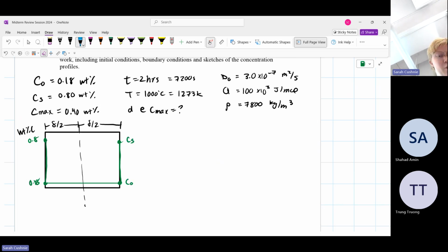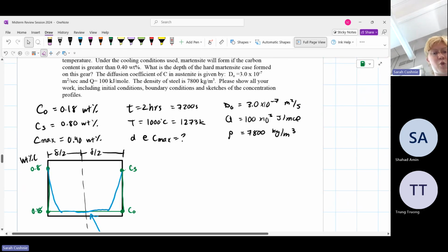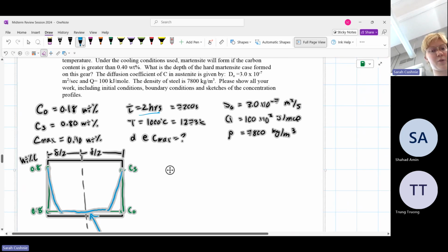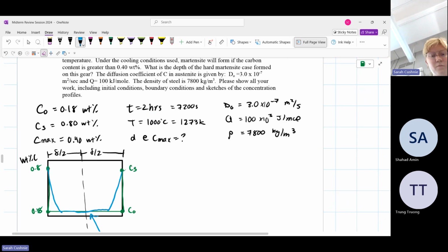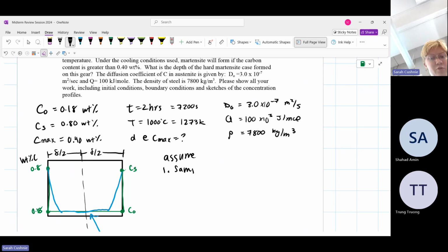And then over time, we're going to have it diffuse in to form our martensite, or to form the potential for martensite, increasing the concentration. But note that we're still going to have that initial concentration in the middle. And we're going to assume that it's never going to reach the long-term solution here because we're only heat treating it for 2 hours. So that's one of the assumptions we're going to start by making: assume 1. Sample is large.